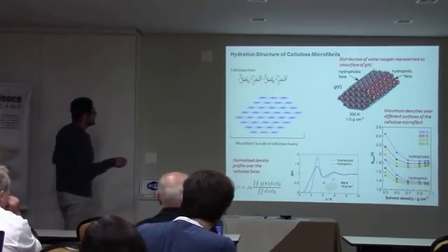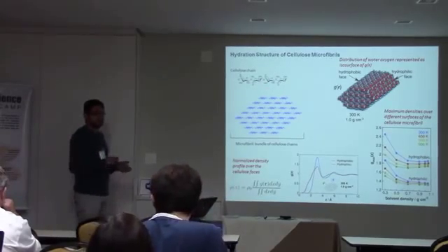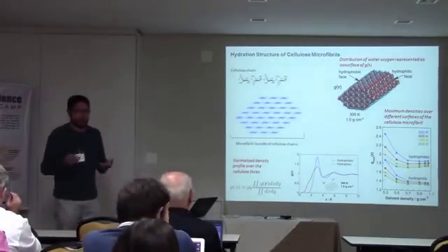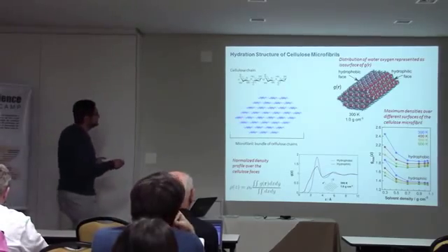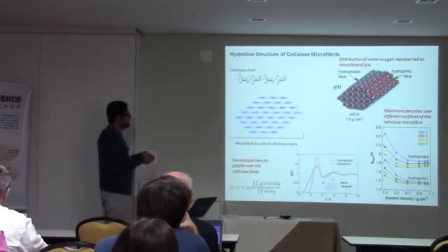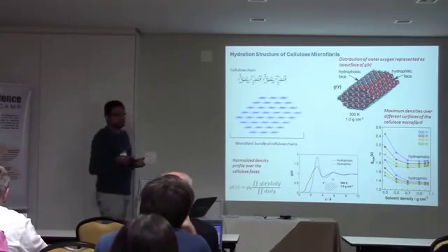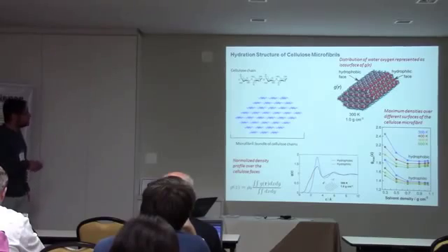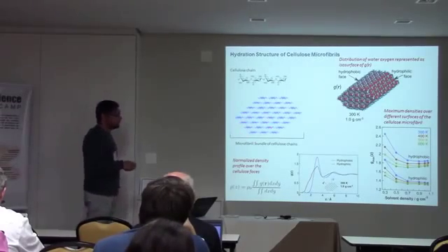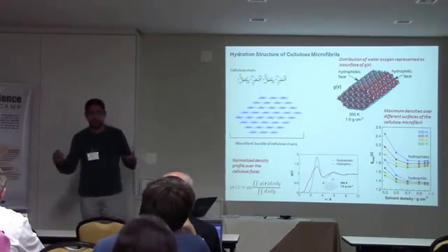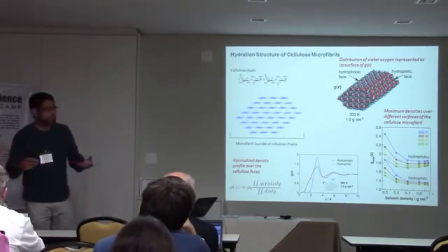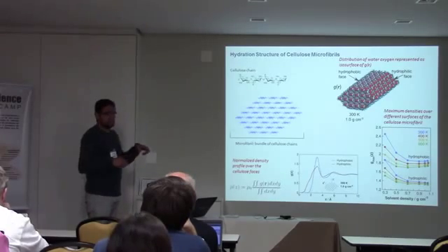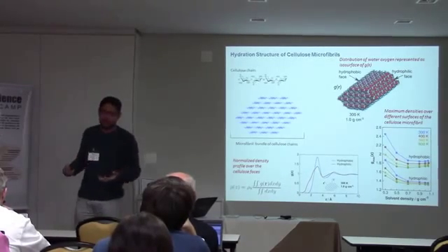So here we have a hydrophobic face. Although it's not strictly hydrophobic, you have fewer hydrophilic groups than on these other faces. So we have essentially two kinds of faces in this kind of fiber. Then we immerse this fiber in a bath of solvent, and we compute the solvation structure around it. So here you have the three-dimensional distribution of water around the cellulose.